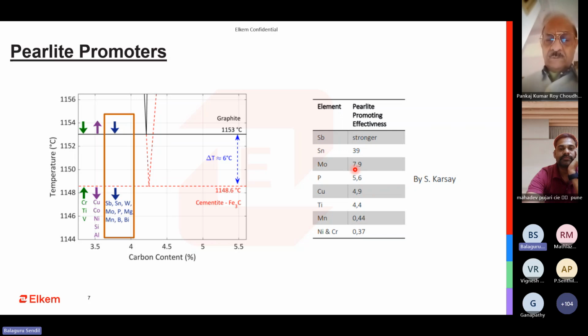So if you have more of this particular element, you can actually further reduce your manganese. Let us come to a scenario where you have a charge mix or a scrap that you have procured, which has a higher amount of this particular element. You typically tend to keep a bath manganese of this much, and suddenly you see that you have a high amount of pearlite.